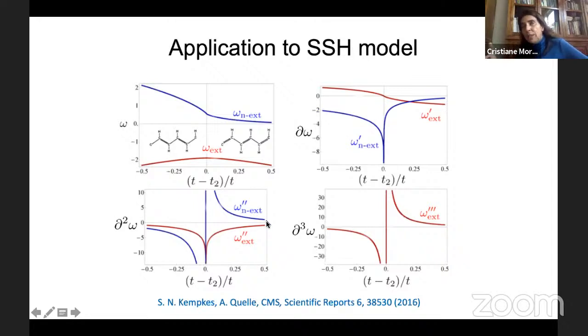So for the other 1D model that we have, we get precisely the same features. Another important thing to observe is that these features appear independently of the parameter with which I am taking the derivatives. I can take derivatives with respect to different parameters that could be driving my phase transition, and I would see the same result.